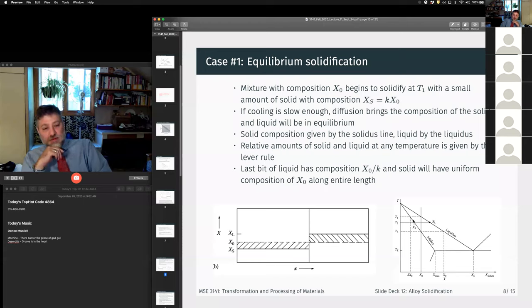composition at T1, X_S here. So at this temperature, the composition is equal to our partition coefficient times our initial composition, right? Because our liquid here is still at X naught, and our partition coefficient is the ratio of the solid divided by the liquid composition. So from that, we can see that at our T1 line here, the composition of our solid is just our partition coefficient times our average composition, right?